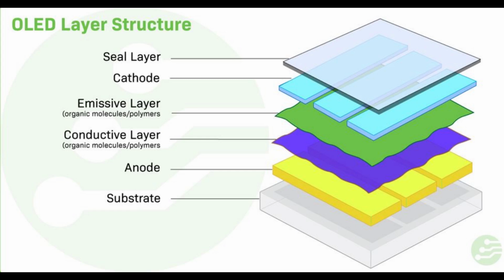In TEOLEDs, the microcavity effect commonly occurs, and when and how to restrain or make use of this effect is indispensable for device design. To match the conditions of constructive interference, different layer thicknesses are applied according to the resonance wavelength of that specific color. The thickness conditions are carefully designed and engineered according to the peak resonance emitting wavelengths of the blue, 460 nanometers, green, 530 nanometers, and red, 610 nanometers, color LEDs.